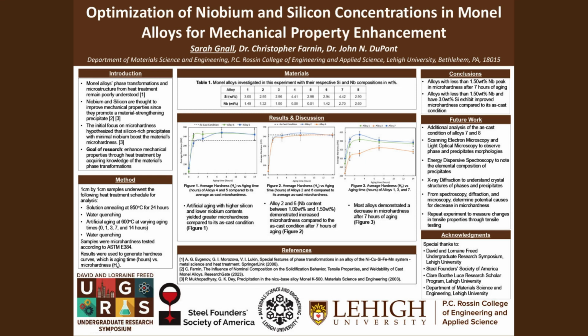Typically, these materials are used in the as-cast condition. However, the phases present in Monel alloys and how these phases form as a result of a different type of material processing called heat treatment remain poorly understood. Heat treatment is used to improve hardness and other mechanical properties, which subsequently increases the material's life cycle. Heat treatment generates precipitates through a phase transformation process called precipitation hardening, allowing the material to be stronger.